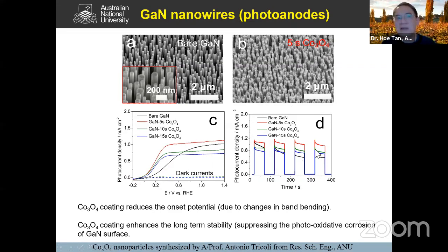But if you look at this plot here, which is more important, you can see the black curve, which is the bare gallium nitride, you can see the degradation. Okay, the photocurrent degradation with time. Okay, which means what happens is the electrolyte is etching the nanowire. Okay, so the photocurrent starts to drop. But if you passivate it with some cobalt oxide, then you can see that not only does it enhance the photocurrent, but the stability is significantly enhanced. So now we essentially have a longer lifetime photoelectrode compared to the one without any cobalt oxide on top. So this is the gallium nitride nanowire for photoanode.